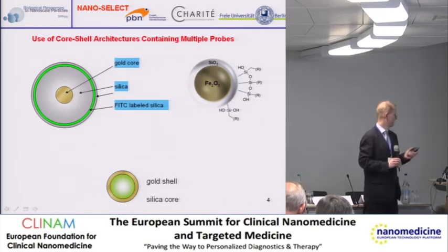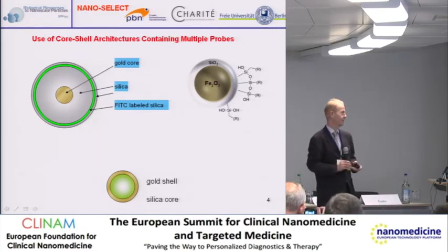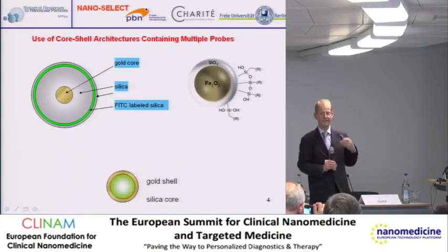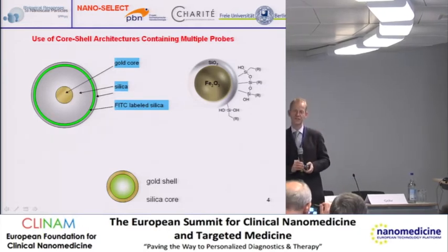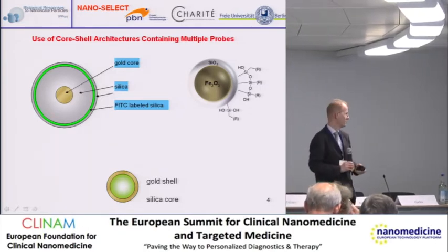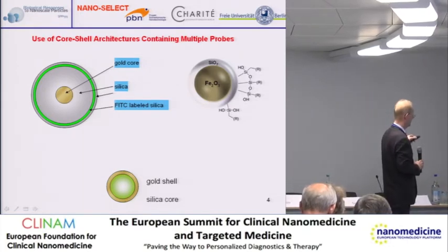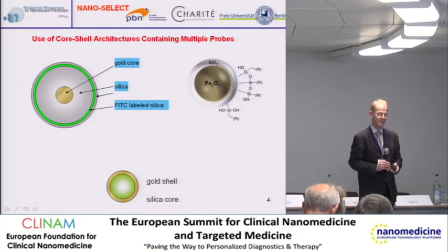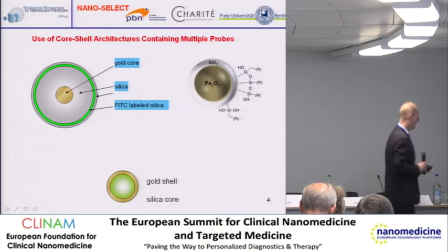This is a more complicated architecture of particles that we use, because in the middle there is a gold core. This is, as a high Z material, advantageous for X-ray absorption. And then we also can bind either quantum dots or dye layers, and then we can surface coat the entire system as we like. So the internal structure is quite important.